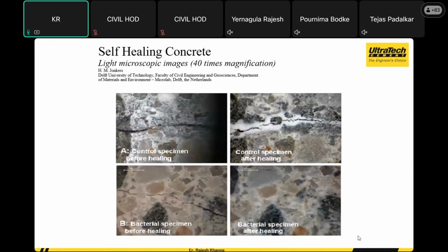And if you can see these microscopic images, there is a crack in the figure, and slowly it has been healed out, and you could see the bacterial specimen after healing. So you could see as if there is no crack on it. So it doesn't happen overnight. It takes some time to do it.